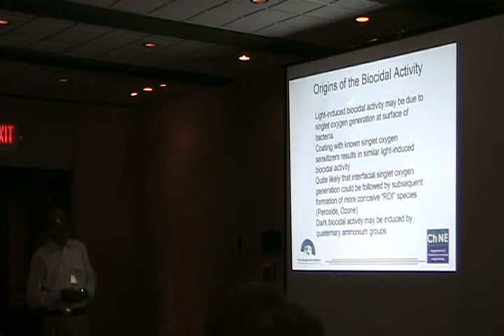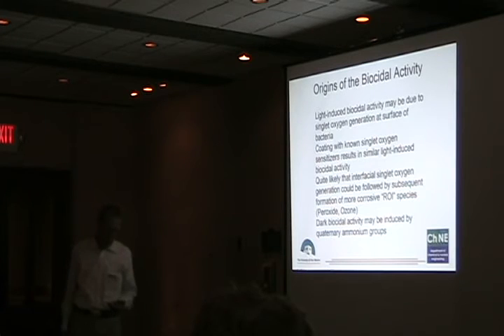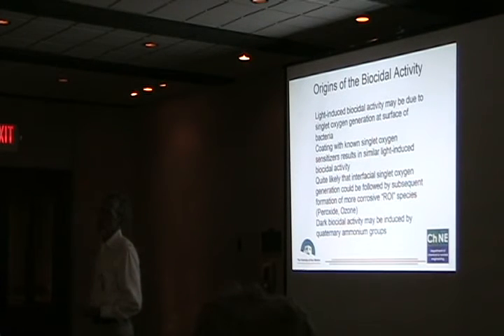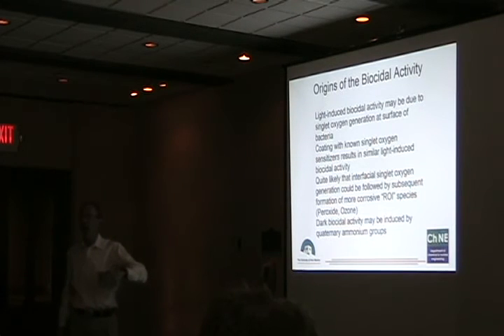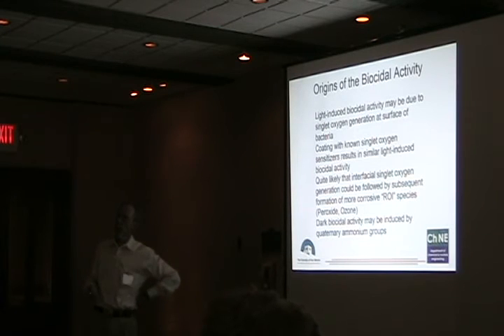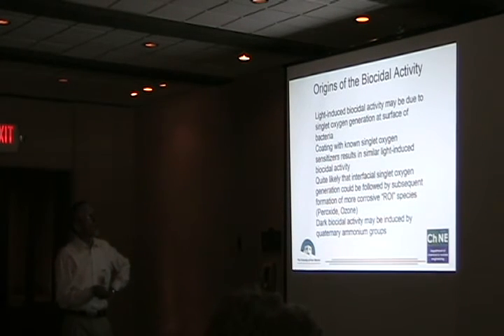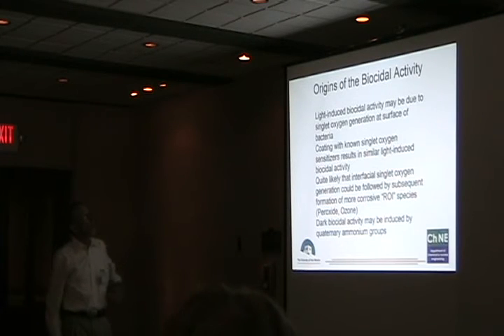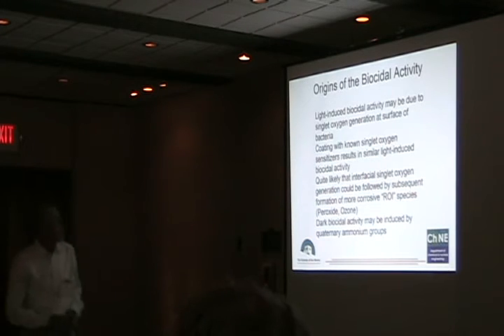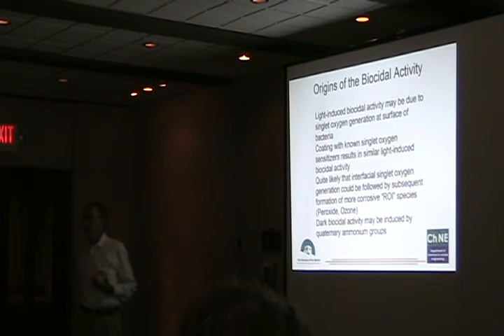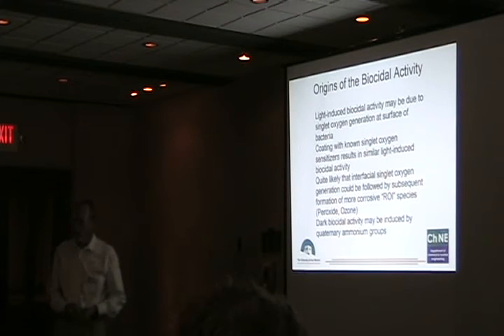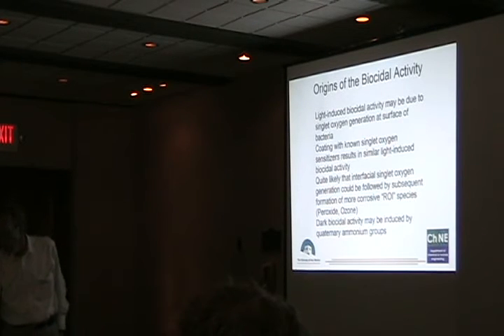On the other hand, we can't rule out at this point that the light-induced biocidal activity could occur by a charge transfer mechanism. We have, of course, the polymer that's cationic, and we have halide ions, and so a reasonable possibility would be an electron transfer from, say, a chloride ion to the excited polymer, and then escape of the chlorine atom, and that would be very reactive towards bacteria. We're trying to do experiments now, but it's not as simple as we'd like, because of course we need to find a bacterium that's killed by the polymer, but also is not killed by the absence of oxygen. And we actually have worked with one bacterium that we think will fit the bill.